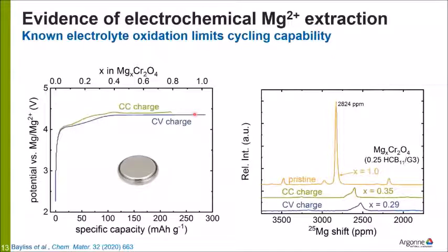during this process. However, we went ahead and analyzed the resultant material with NMR, and so this orange line at the top is the pristine material, and this peak represents magnesium within the tetrahedral site, NMR being both site and elemental specific. During both the constant current and constant voltage charging, we see this peak shift, which is indicative of the chromium redox occurring, but also the volume of the peak decreases dramatically, indicating that the magnesium is no longer found in the tetrahedral sites.